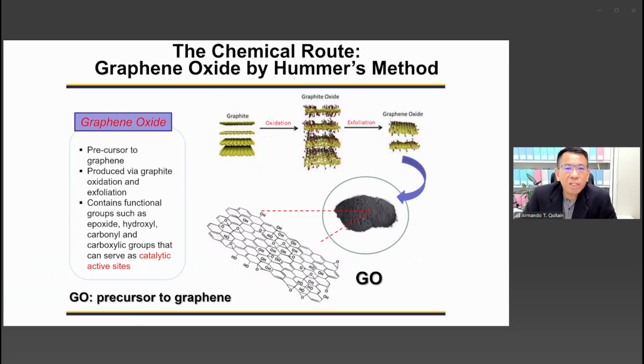All right. The problem with graphene being isolated from graphite is that it's not an economically feasible method, or I should say not a cost-effective method. As an alternative, we can also apply the chemical route. And one of the chemical routes that we can think of for production of graphene is by Hummers' method. But this involves oxidation of graphite. When you oxidize graphite, it will form graphite oxide. This is graphite oxide in its form. It has those layers of graphene oxide. You exfoliate those layers of graphene oxide, you get graphene oxide.